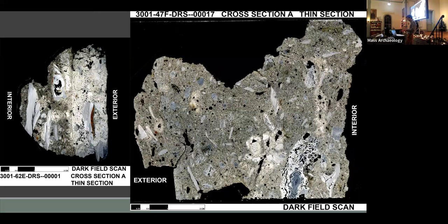And basically, after the walls were created and allowed to set and harden, the tabby had to be protected by a layer of stucco. While permeability was necessary for tabby to harden and gain strength through exposure to air, it also allowed water from rain, humidity, and rising damp to seep into the pores and accelerate these processes of erosion. So to minimize the threat, tabby structures were often coated in two or more layers of tabby plaster made from oyster shell lime and fine sand.